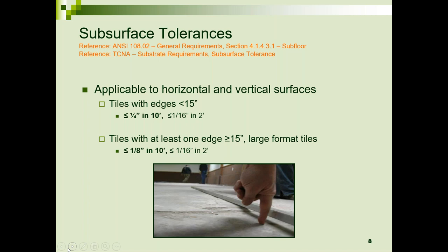For large format tiles, the requirement is 1/8 inch in 10 feet. For tiles smaller than 15 inches, 12 by 12, for example, it's 1/4 inch in 10. But with today's finishing and placement methods for concrete, generally the best you're going to see is 1/4 inch in 10.